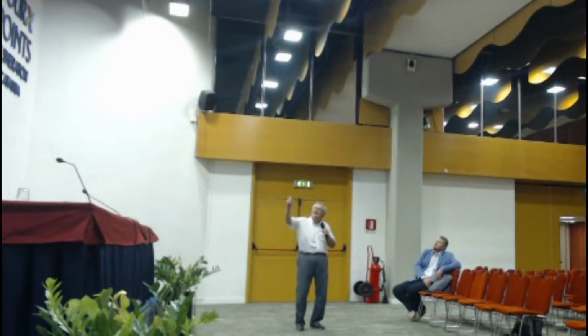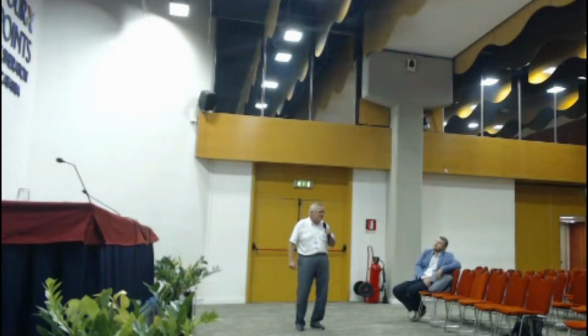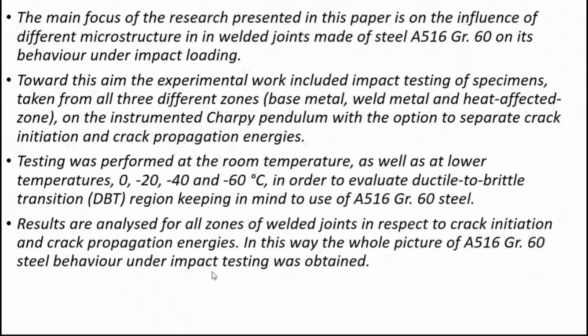So this is what is also written here. We have used an instrumented Charpy toughness pendulum, which can separate crack initiation and crack propagation energy, which is a very important issue. As it turned out in this case, not so important for what we aimed to do.